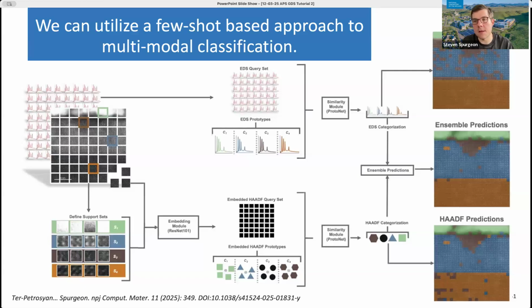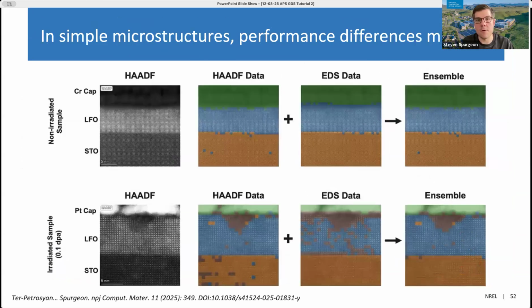And so what we find is that, as you might expect, looking at one modality or another is often outperformed by the ensemble approach, but it really depends on the microstructure. So for example, when we look at this material pre-radiation, the microstructure is relatively simple. It's just kind of a layer here. And so if you looked at classification just based on the imaging or just based on the spectroscopic data, the result is relatively similar. However, when the microstructure is damaged by radiation, when it's more complex, then these models independently tend to perform more poorly than if we ensemble them.